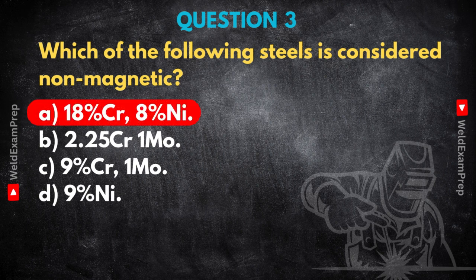18 to 8. That rings a bell. Isn't that like common stainless steel, like for sinks or cutlery? Exactly. That composition, 18% chromium, 8% nickel, is typical for austenitic stainless steels like grade 304 or 316. And why is that type non-magnetic when the others are? It comes down to the atomic structure. Austenitic stainless steels have what's called a face-centered cubic, or FCC, crystal structure. At room temperature, this structure just doesn't support strong magnetic domains. It's inherently non-magnetic. Ah, the crystal lattice itself.